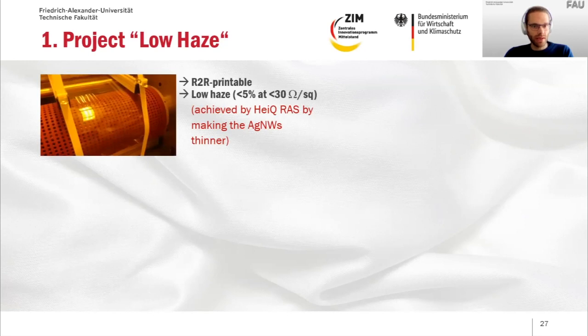So we had 2 projects together with HeiQ RAS to develop organic photovoltaics with their ECOS nanowire inks. The one is called low haze. There we developed the roll-to-roll printing process for the silver nanowire coatings with a very low haze value, so less than 5% diffuse light. And this was achieved by HeiQ RAS by making the silver nanowires thinner, down to 30 nanometers in diameter, which is the main driving factor for creating a hazy appearance.